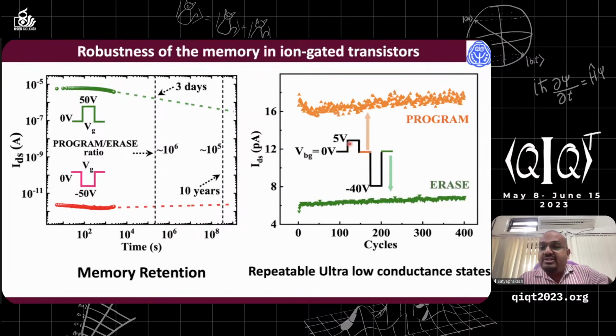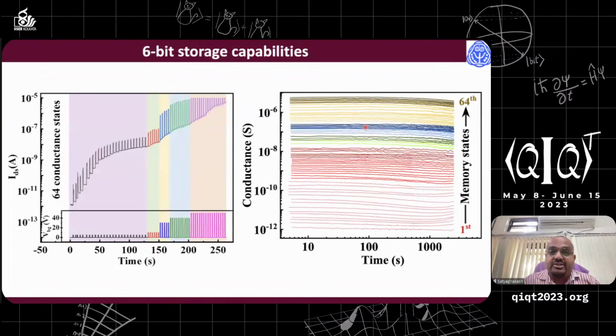What is important here? We have applied a pulse train, say 5 volt and minus 40 volt, and we have read this. And you see, when you do this experiment, for a 5 volt read, you see the current is picoampere, and it is consistent over a period of 400 cycles. It is a small current of picoampere, the state repeats itself, which is very good as far as the memory is concerned.